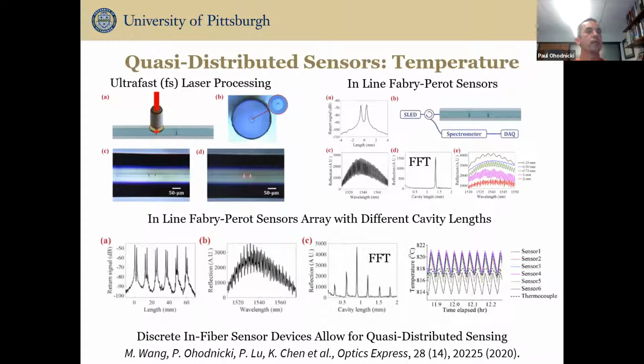So we can go from a point sensor to a quasi-distributed sensor. This is where we take this type of a device and we now spread it along the length of an optical fiber. This is actually work by Kevin Chen's group, and I've had a chance to collaborate with him on this over the years. This is where you actually can inscribe the equivalent of a Fabry-Perot interferometer in the core of the fiber, and then you can space those along the length of the fiber.